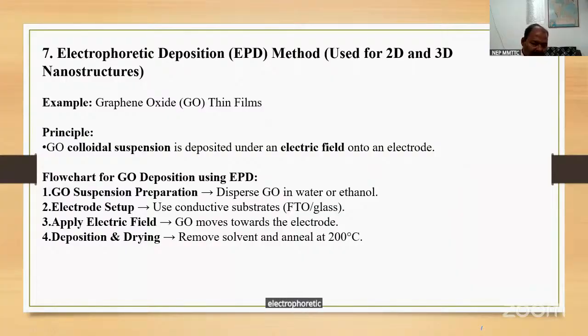Electrophoretic deposition, that is the EPD method. This is used for 2D and 3D nanostructures. Graphene oxide thin films. Okay. We can use this one. So here the GO thin films, a GO colloidal suspension is deposited under an electric field onto an electrode. This is the flow chart for GO deposition using electrophoretic deposition.